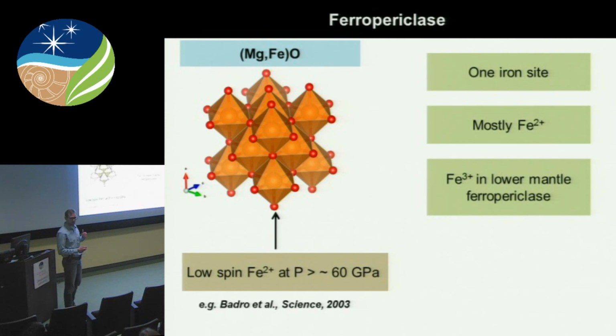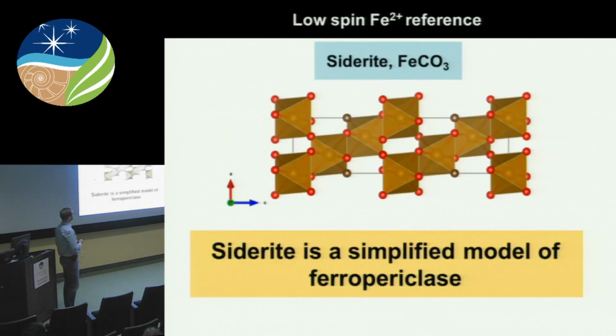Here is the crystal structure of ferropericlase, the second most abundant mineral in the mantle. The crystal structure is pretty simple. It has only one cation site for iron. This iron is mostly Fe2+. However, lower mantle ferropericlase usually has some amount of Fe3+ that complicates the matters quite substantially. Ferropericlase has a well-documented spin transition at room temperature. It's believed to be low spin at pressures of approximately 60 GPa.